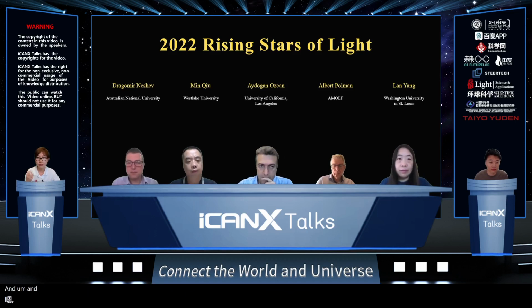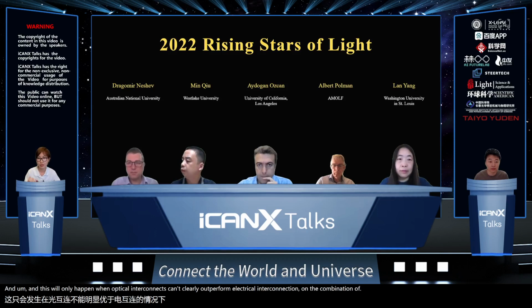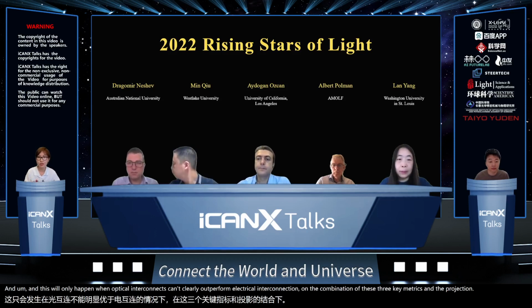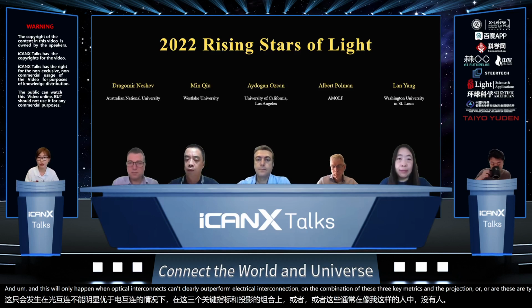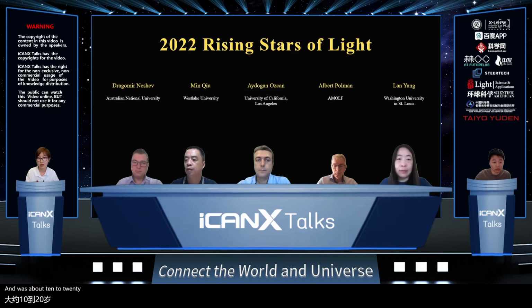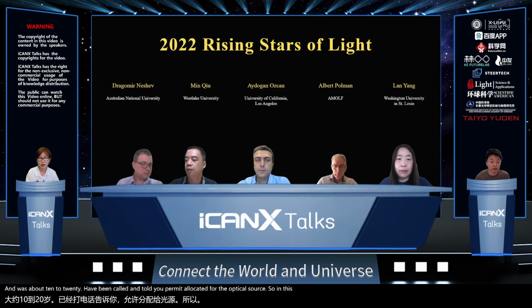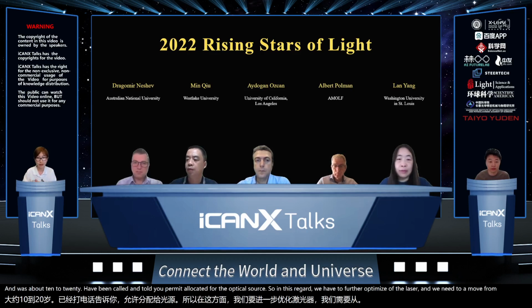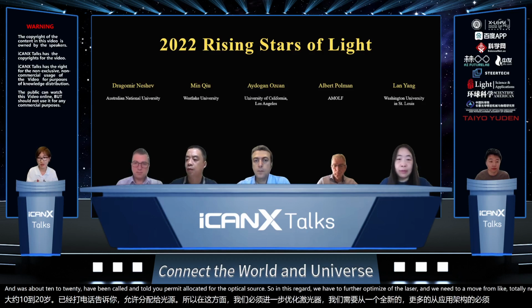And this will only happen when optical interconnects can clearly outperform electrical interconnects on the combination of these key metrics. The projection typically means a 100 femtojoule per bit system energy target, with about 10 to 20 femtojoule per bit allocated for the optical source. So in this regard, we have to further optimize the laser, and we need to move from these aggregated architectures to being integrated on the photonic circuits.